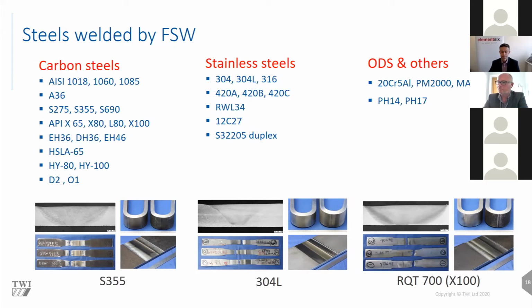We're not melting the steel at all. We're not changing the chemical composition. And so the carbon equivalent has far less influence upon the process with friction stir than other kinds of welding process. We then did the same kind of thing with stainless steels. So we started with simple stainless steel, such as 304, followed the same process, gradually moving up through the complexity of the alloys, and finally finishing with things like duplex and super duplex stainless steels, and found that we could weld them quite easily.